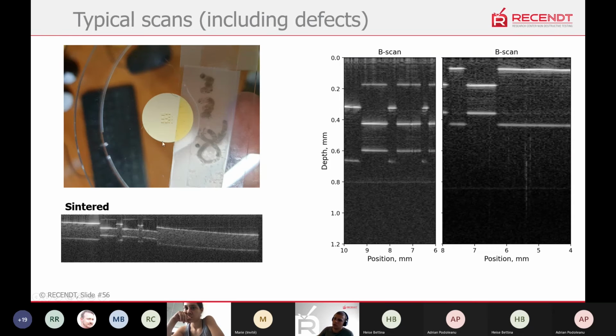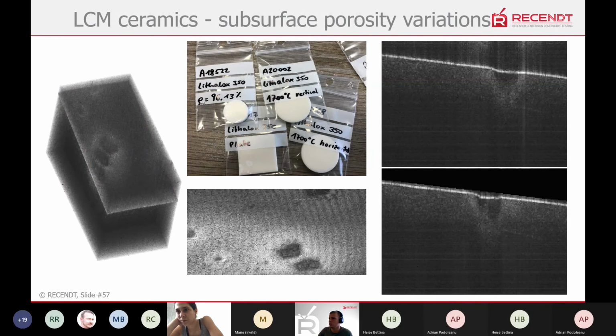And we tested also such green parts, so it's more or less polymer matrix with some ceramics inside. Yeah, and we could detect all the layers. So here it's around 600 or 700 micrometer thick, and this is already a sintered sample from these green parts. It worked quite well, and also to detect some defects. This is a quite interesting defect. It's some subsurface porosity variation, which occurs during the 3D printing process, and it was possible to access the depth profile of these variations, which is of interest for this ceramics community.